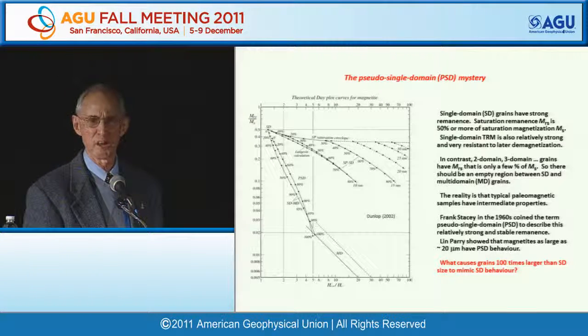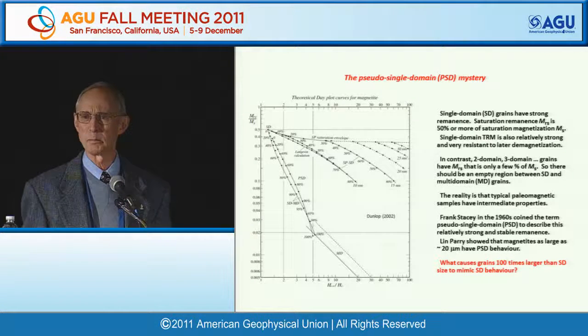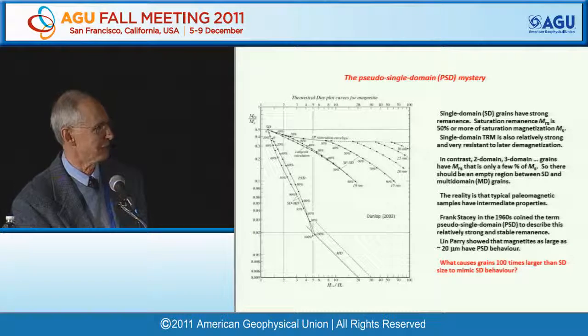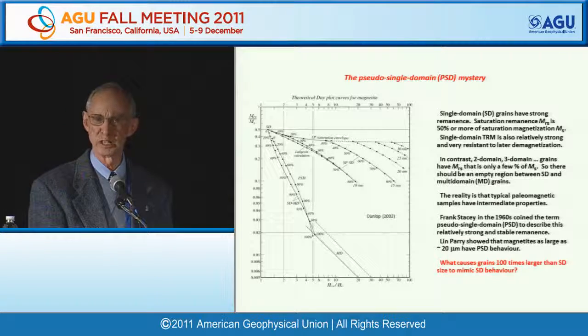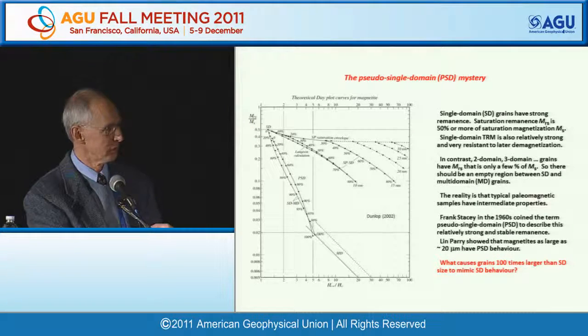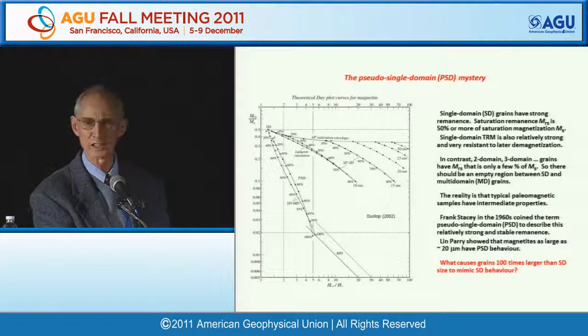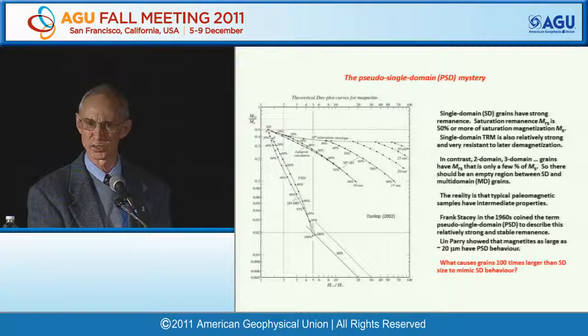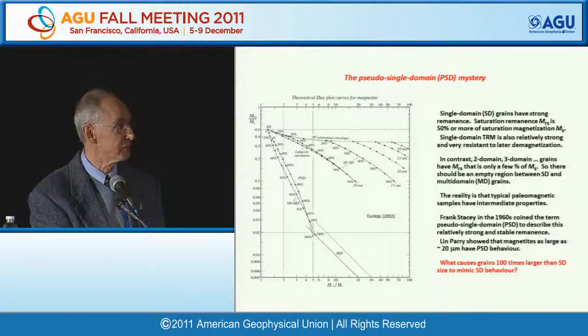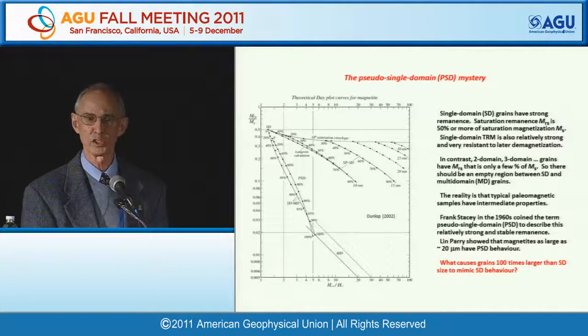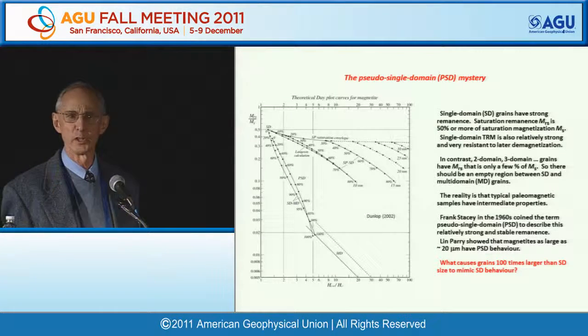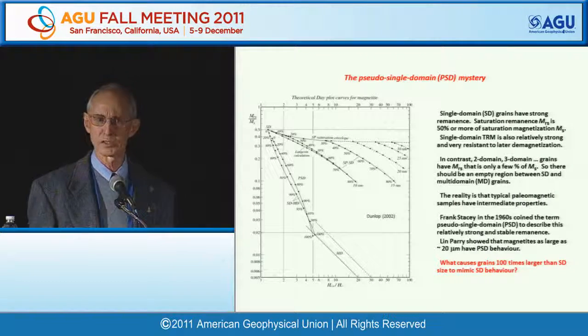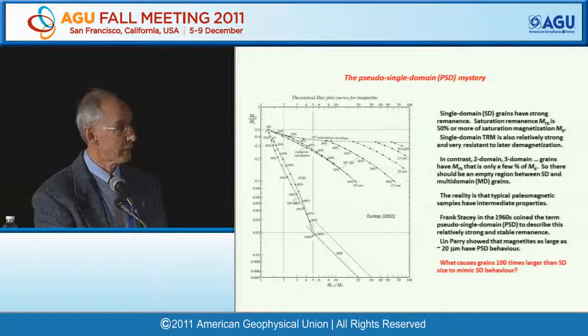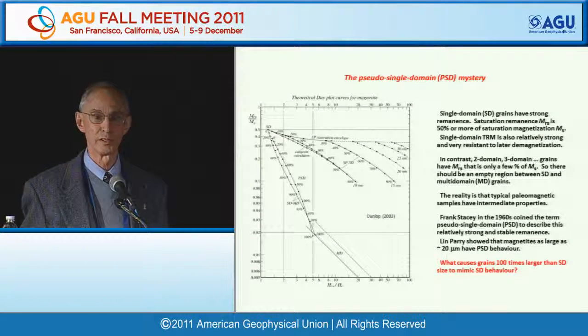I had to, of course, show a Day plot, and even if you don't know what a Day plot is, that doesn't matter. I like Day plots. And in this upper corner here should be all the single domain grains, because they're very magnetically strong. Down at the bottom where things get weak, that's where the two domain, three domain, multi-domain things should live. And in between should be a no man's land, or no particles land. Nothing should land there. But of course, what we find, I was looking around in the posters in the hall today at all the Day plots that were there, and every single one of them had all of the magnetite points in the middle between the two. That's where they all live.